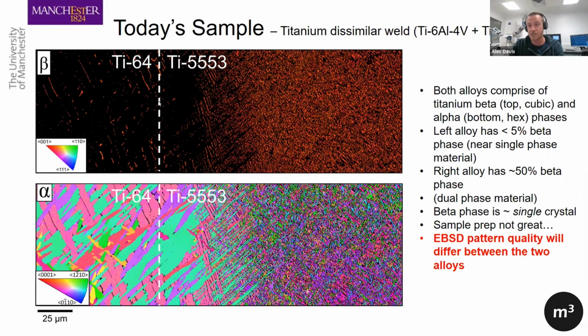And this is useful for us for this demonstration. The other thing to note is that in the Ti64, the beta phase is very small. We've only got about 5 volume percent here. But in the 5553, we have about 50% beta. Now, what becomes important is that because the alpha and the beta phases in the 5553 are so well interwoven at a nanoscale, this affects how our EBSD patterns behave. But on the Ti64, we're mostly just scanning the hexagonal phase, so we get much stronger patterns. So the key thing to note is that we get different strengths of patterns, and the way it behaves is down to how the electrons interact with the material.